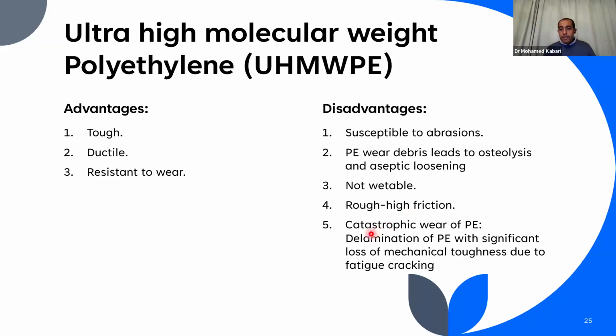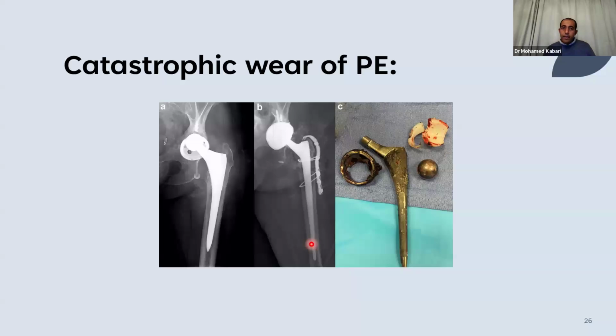And sometimes it can lead to catastrophic wear of the polyethylene, where there is delamination of the polyethylene with significant loss of the mechanical toughness due to fatigue cracking, like we can see in this picture, where the polyethylene was broken, and we can see it in the X-ray. There is a collapse of the head into the acetabular cup, and after removal in surgery, we can see the catastrophic wear that happened to the polyethylene.